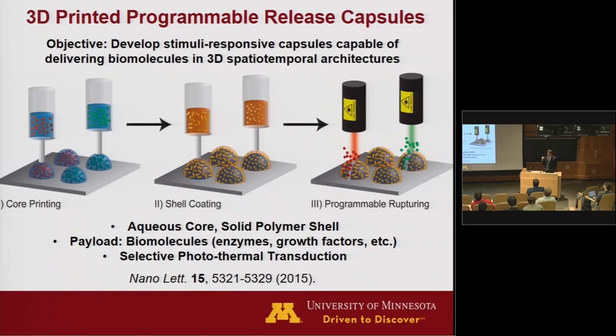So one crazy way to think about this is, let's say you have a collection of stem cells within a matrix, and you shine a red laser on it, and now it differentiates into a heart, and you shine a green laser on it, it differentiates into a liver, something like that. Obviously, we're nowhere near that, not even close, although we have shown now differentiation using these capsules and cell migration as well using these capsules. These are ongoing projects. But the trick here is that this should be orthogonal, so the red laser should only trigger these guys and not these ones. The green laser should only trigger these guys and not the other ones.